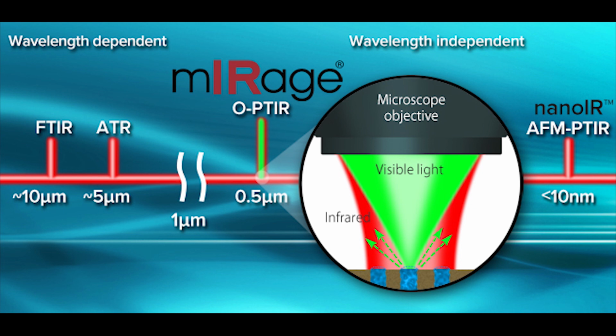There is a question about how differing materials will respond thermally in different ways. How are these correlated in the data collection? It's true that the photothermal response of a sample will depend on both the IR absorption coefficient and its thermal properties, for example, its thermal expansion coefficient, or how much the index of refraction changes with temperature. And so if you are looking at just a single wavelength image, it may be hard to discriminate whether your contrast is coming from IR absorption differences or the